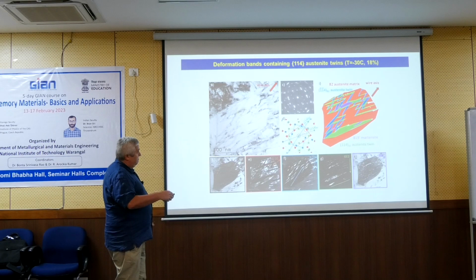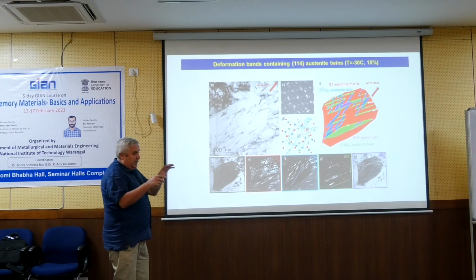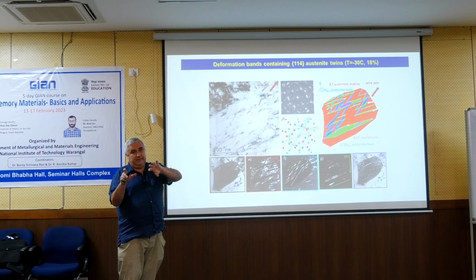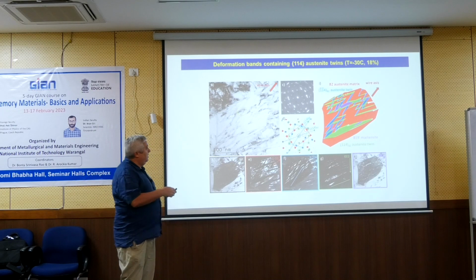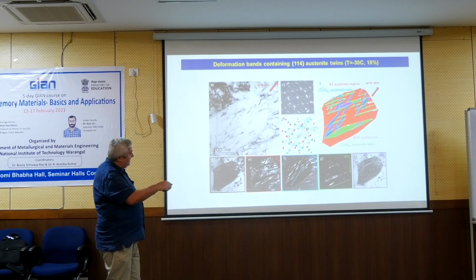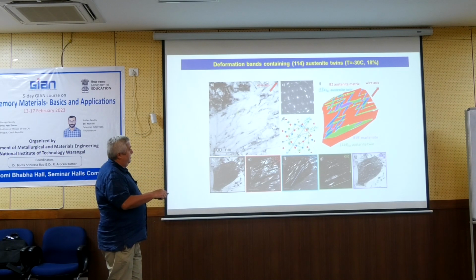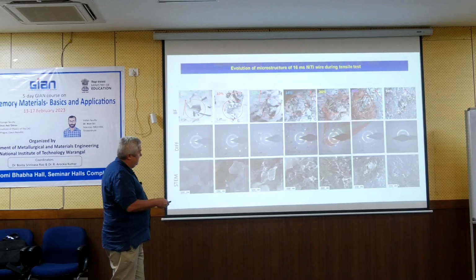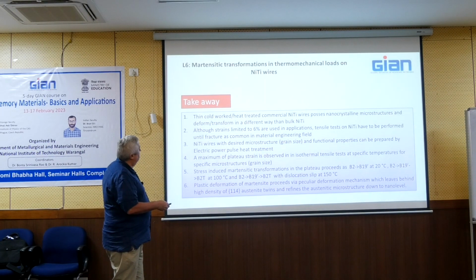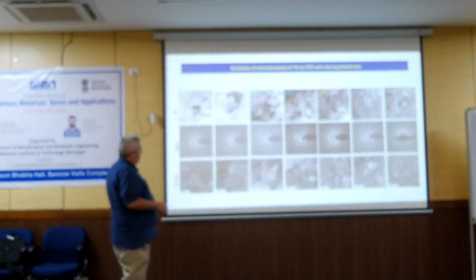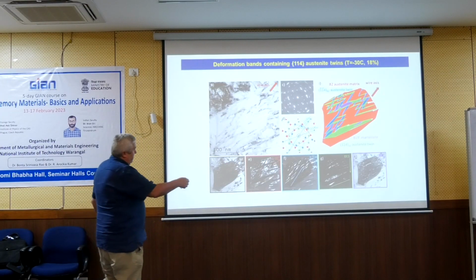And we see that the red is the original parent austenite, and blue and green are these kind of misoriented matrices. So if you have such kind of microstructure in the grain, then, and I have it somewhere maybe a little bit down. Okay. No, it's not here. It's different. I will show it differently. But okay,